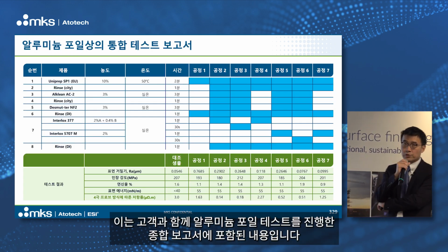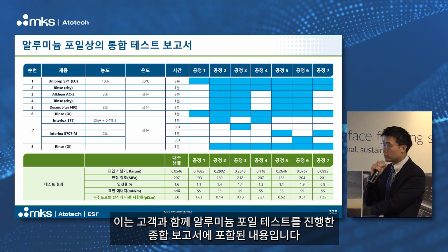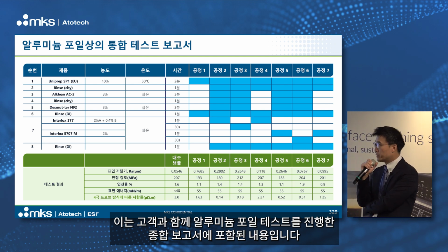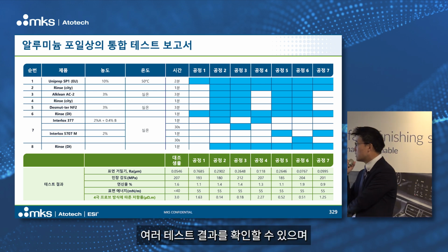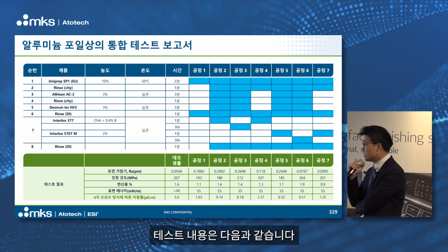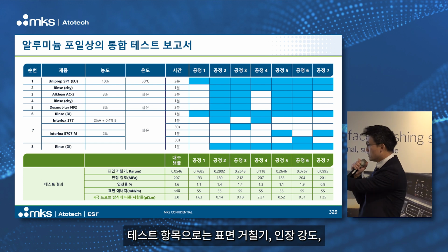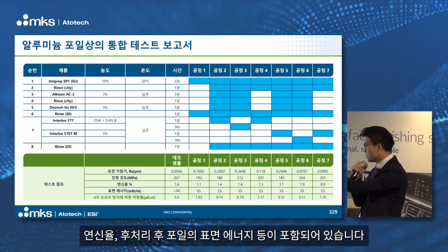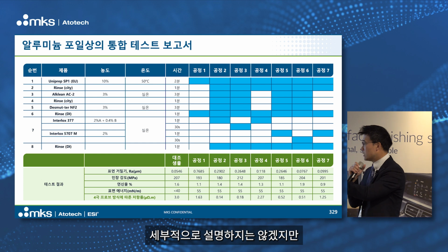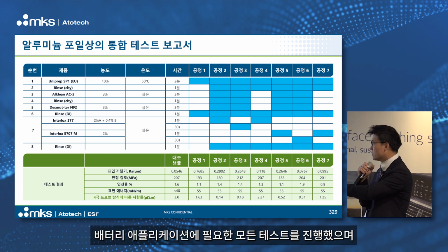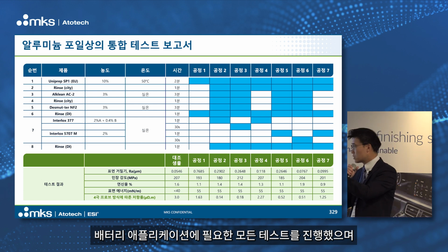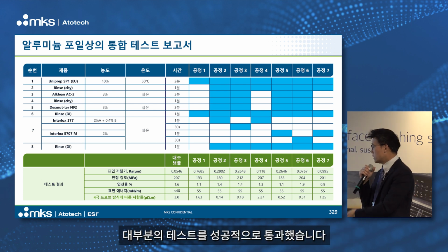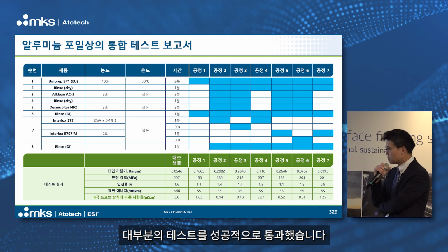So this is a consolidated report together with our customers on this test of aluminum foil. And you can see that there are different tests that we've done. At the bottom, there's surface roughness, tensile strength, elongation percentage, surface energy of the foil after all this post-treatment. And I won't go into details again. All the tests are according to the battery application, and we can pass most of them.